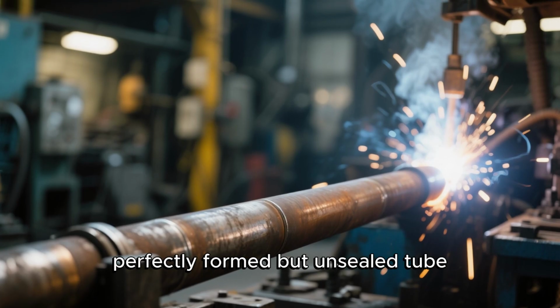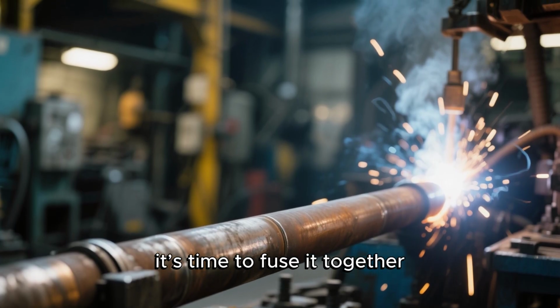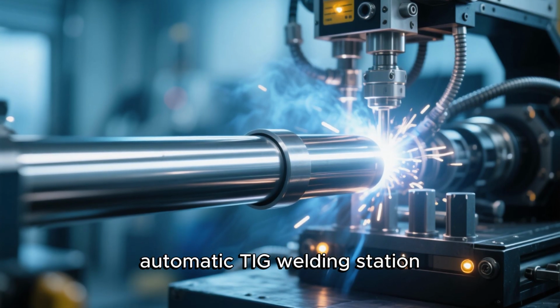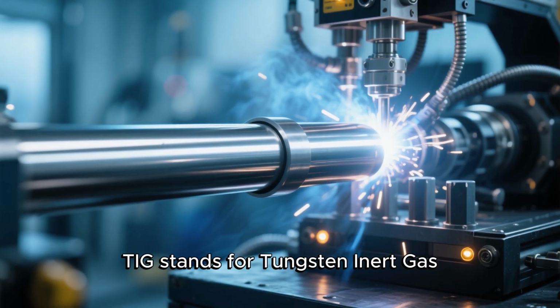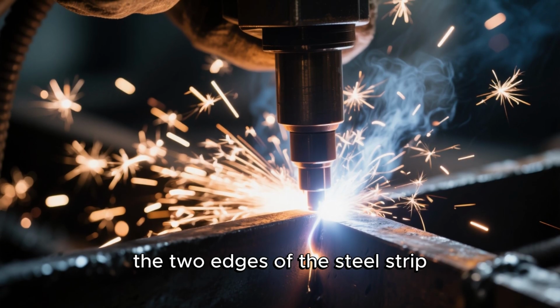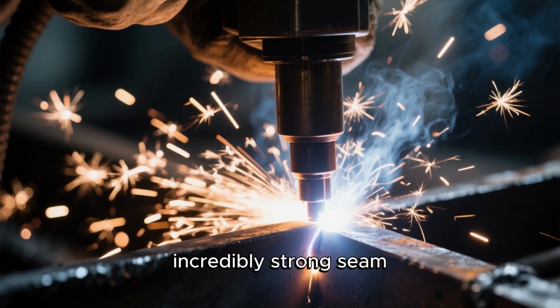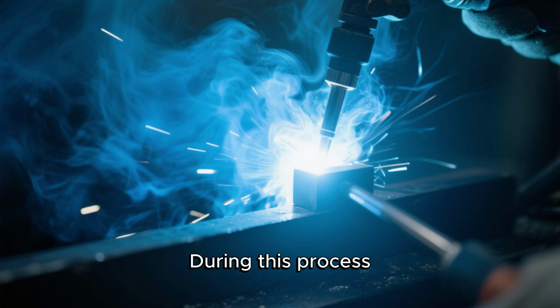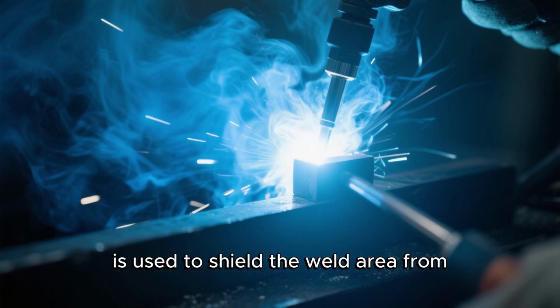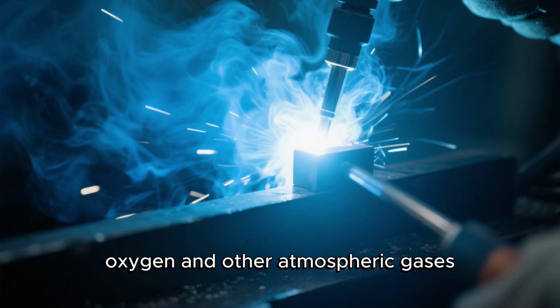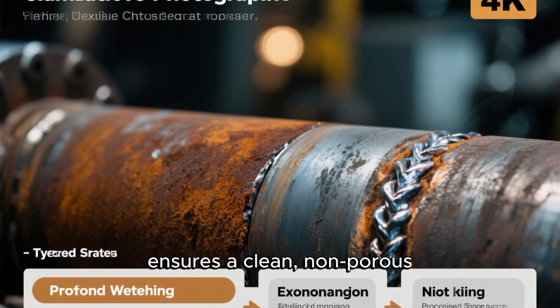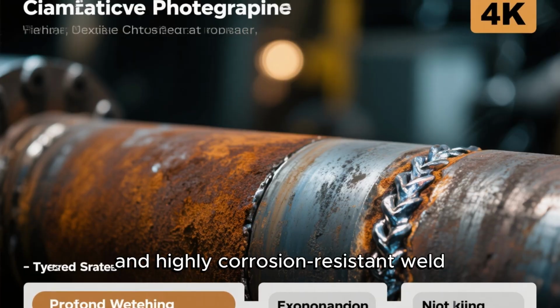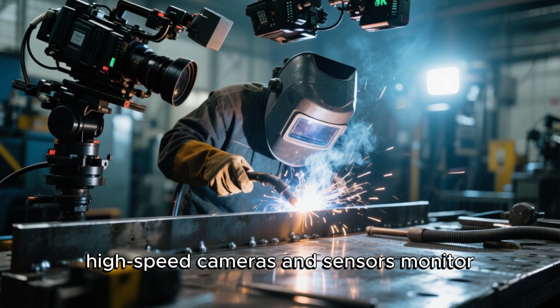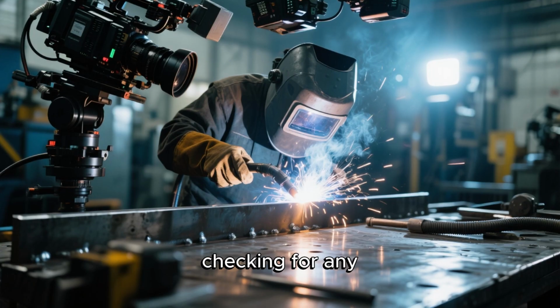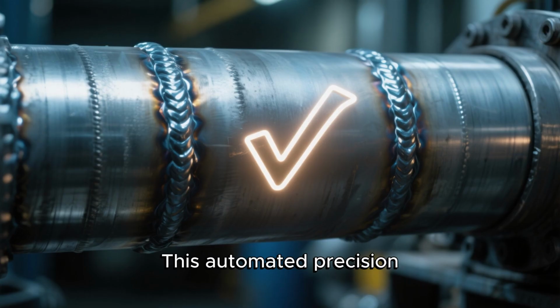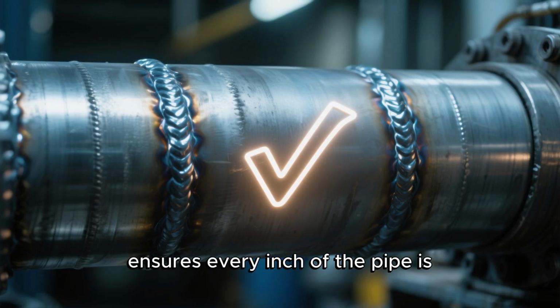Now that we have a perfectly formed but unsealed tube, it's time to fuse it together. The tube moves seamlessly into the automatic TIG welding station. TIG stands for tungsten inert gas. A high-frequency electric arc melts the two edges of the steel strip, fusing them into a single, incredibly strong seam. During this process, an inert gas, usually argon, is used to shield the weld area from oxygen and other atmospheric gases. This prevents oxidation and ensures a clean, non-porous, and highly corrosion-resistant weld. To guarantee perfection, high-speed cameras and sensors monitor the weld seam in real time, checking for any inconsistencies or defects. This automated precision ensures every inch of the pipe is flawlessly joined.